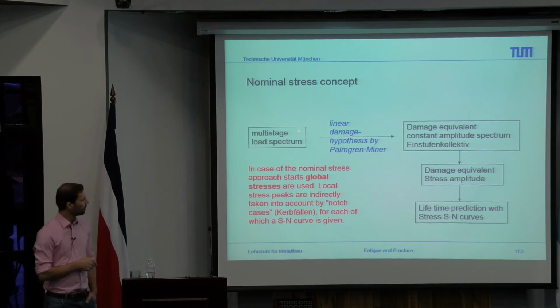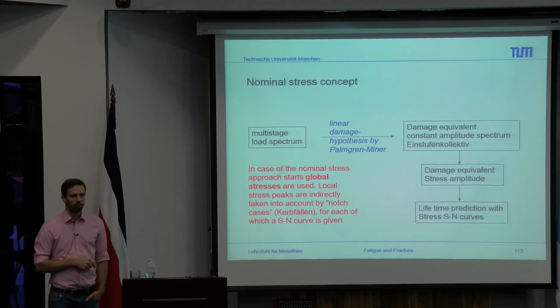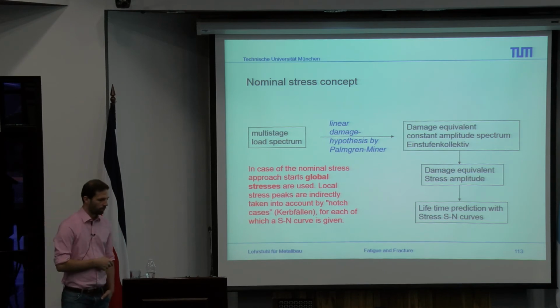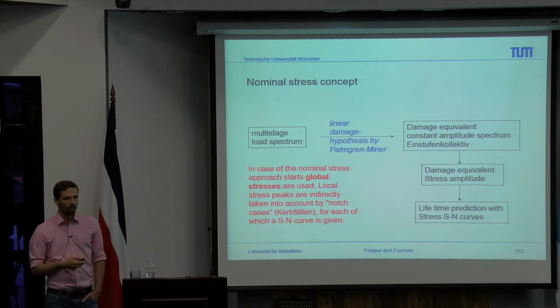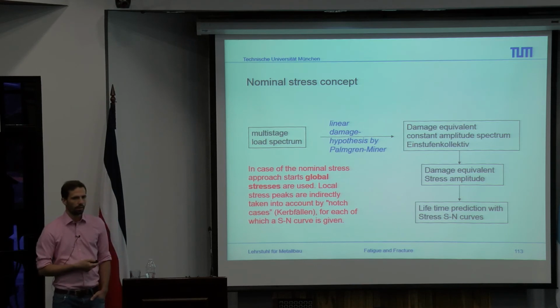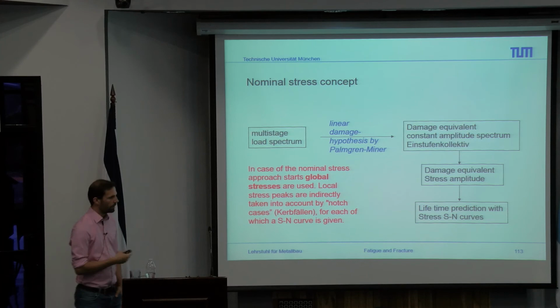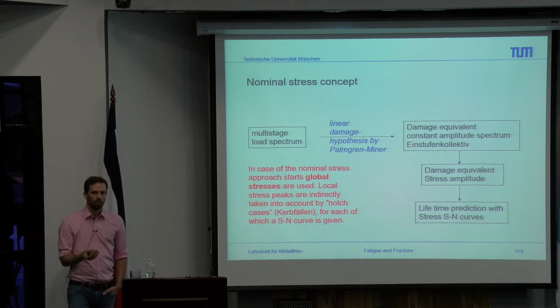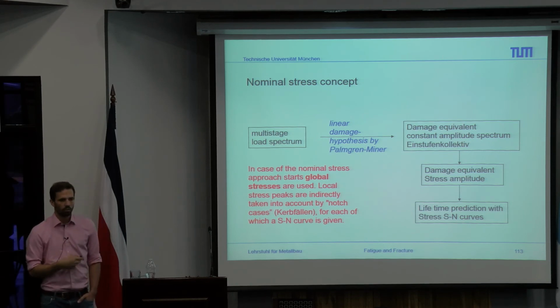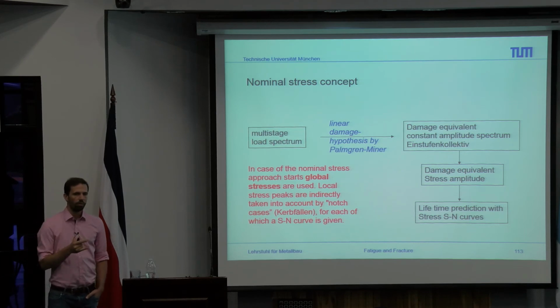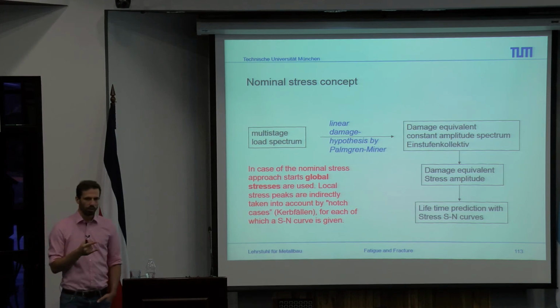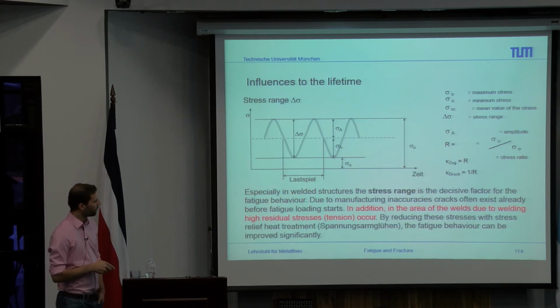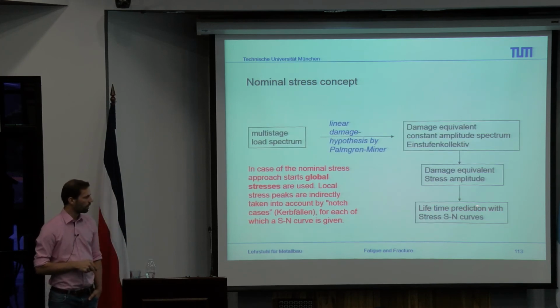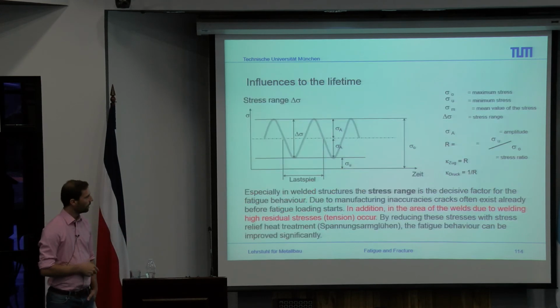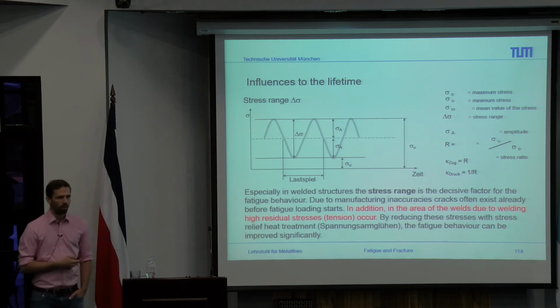Then, due to the multi-stage load spectrum, we have a linear damage hypothesis, which is by Palmgren-Miner. This is something I'm going to show on the next slide. And due to the damage hypothesis, we can also recalculate an equivalent stress range. We say, okay, we have different stress ranges, for example a stress range of 200 MPa and 240 MPa. At the end, due to the damage equivalent stress range, we recalculate a stress range which has the same amount of damage inside your structure. And with this information, we can also give a lifetime prediction due to the stress in the SN curves. So this is the procedure you usually go through for the nominal stress approach.